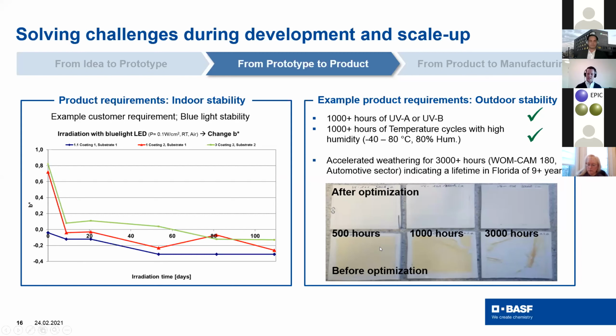And you can see here what happens if you did not optimize your UV coating. So at the beginning, we started doing this. We had UV coatings which are very nicely structurable, but they were not optimized for outside durability, for example. After 500 hours, they were completely yellow, and after 3000 hours, there's not a foil, or not a structured foil, anymore. Here at the top, you have to believe me, yes, there is a structured foil there. After 3,000 hours, the one on the left, I cannot see the difference. It has not been yellowed. So there we made really big steps to outdoor weatherability.